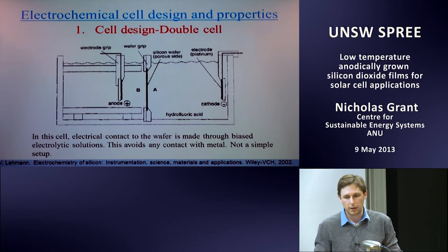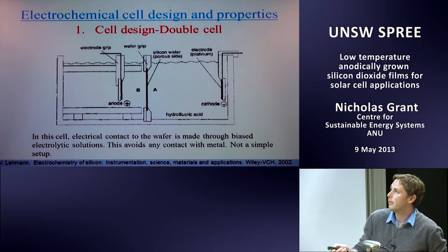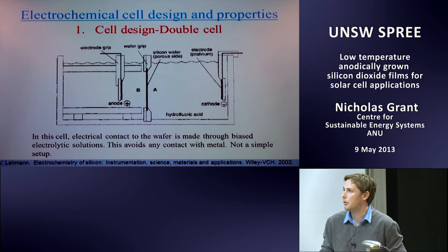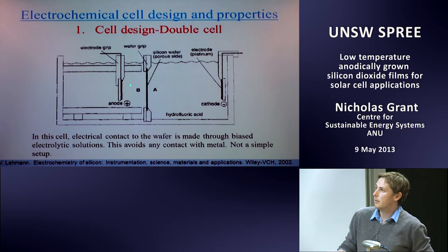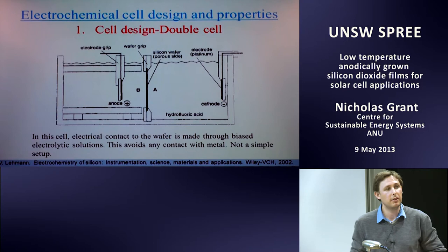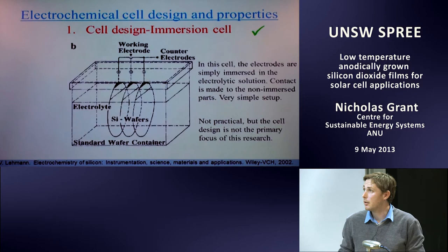Another approach uses two different electrolytes contacting the silicon wafer — one on each side — instead of metal contact. The oxide grows on side B. The advantage is there's no metal contact, limiting contamination. However it's quite complex. Hydrofluoric acid shouldn't be used as it would create porous silicon.